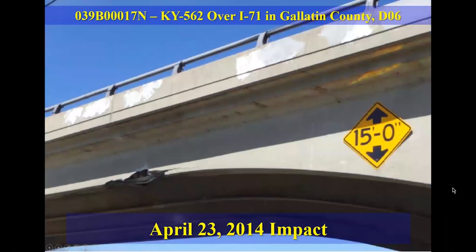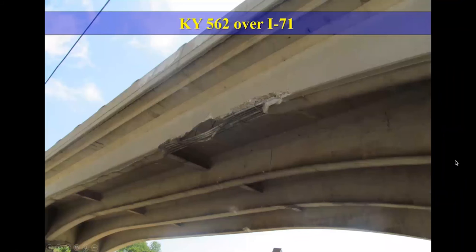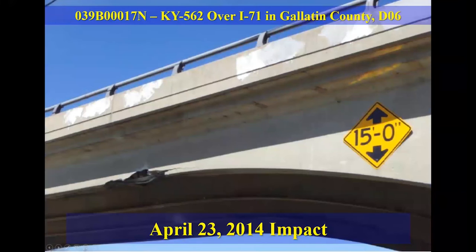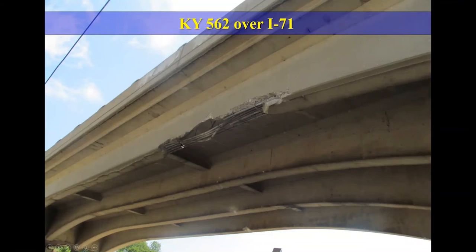I'm going to highlight this bridge. This was impacted twice, once after we repaired it. So this is over I-71. This is the 2014 impact. One of the rebars was heavily bent out of shape, so we had to cut it out, and other bars were slightly bent. So what we did, we removed this bar that was heavily bent and spliced another bar in place. But we needed to replace the strength lost by these bars being bent.